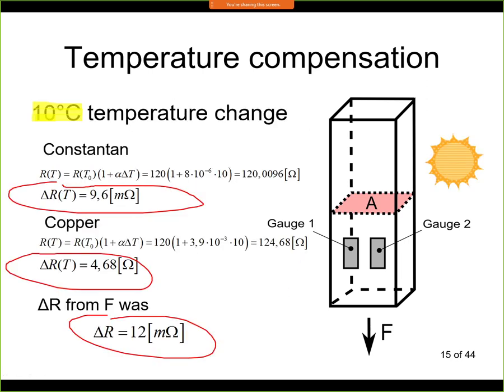Let's take a look at the effect of temperature. Let's imagine that you have a beam, and now the sun starts shining on the beam, or some other heat source heats up the strain gauge. Now if you calculate the change of electrical resistance per temperature change, you will use the temperature coefficient of resistance, alpha here, and for Constantan you will find out that it's about 10 milliohms. So it's approximately the same value as we have from the force. If we calculate the same for copper, we can see that here we have 4.7 ohms.